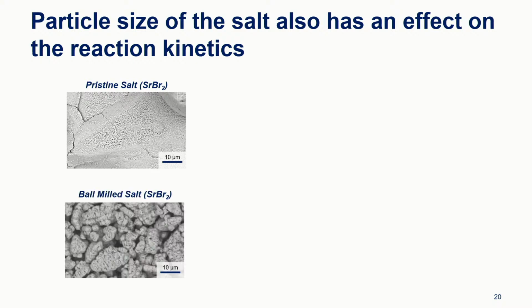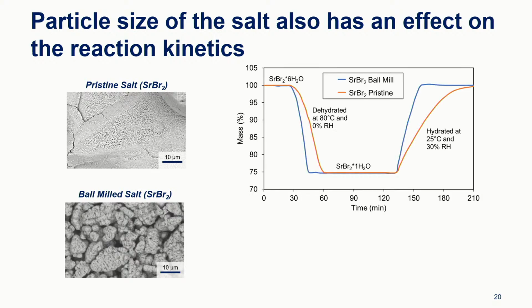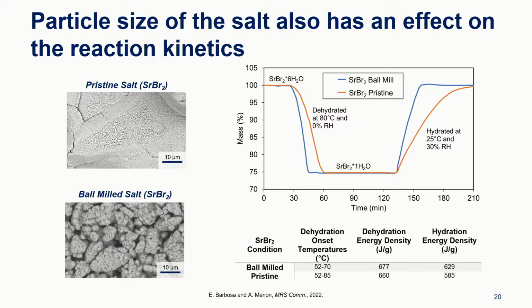And the particle size also has an effect. So working with the larger particles versus ball milling it to get smaller particles that are about 10 microns in diameter, we can see when we do TGA that the ball milled salt dehydrates quicker and hydrates much quicker than the pristine salt. And as a result of that, the energy densities from the ball milled salts tend to be a lot higher than the pristine salt.